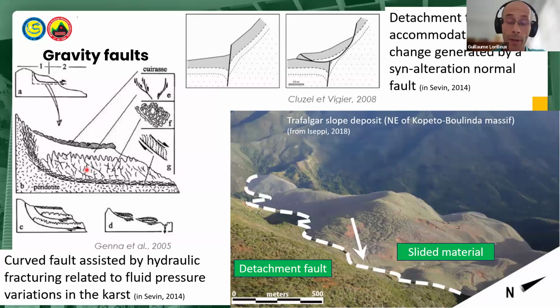Some of these serpentine-filled faults have listric shapes and behaved like drains in their vertical part and acted as barriers in their lower, horizontal part, therefore enhancing the trapping of nickel in the hanging wall of these faults. Such gravity detachment faults can put in contact a double thickness of laterite, as shown on this diagram at the top here, and therefore can be an excellent exploration target. Even though these deposits generally, as I already said, have small sizes, the grade can be really high. This slope collapse may be assisted by hydraulic fracturing and crack-seal veining, that has been described in this paper, related to meteoric fluid overpressure in the hanging wall of the fault.